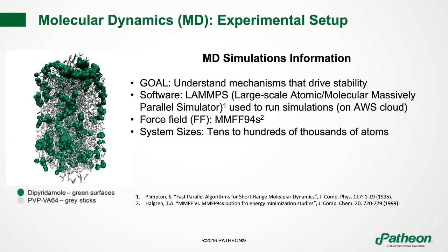And this is the result of a simulation run where we see some agglomeration of drug molecules and some drug molecules that are actually separated and individually placed within the lattice of the polyvinyl pyrrolidone vinyl acetate that you see there in the gray sticks. Now, the PVPVA is not a crystal, obviously. It's an amorphous, and the entire system is an amorphous dispersion.